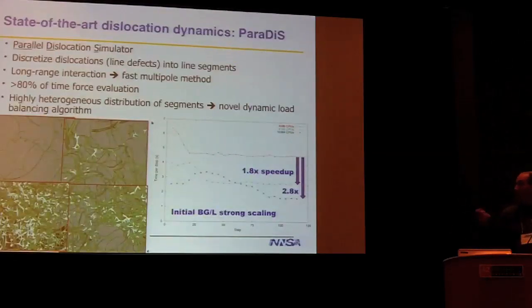Up at the mesoscale, another example from Livermore is the so-called ParaDiS code, which is modeling the dynamics of dislocations within materials. So these are line defects within the material. So instead of modeling every atom in the system, it's modeling the evolution of these line defects over time. This is just showing as the material is strained, the evolution of these, and it becomes very inhomogeneous, and so load balancing is a major challenge. So for this, this has been applied to implement on systems such as the Blue Gene series with some success.